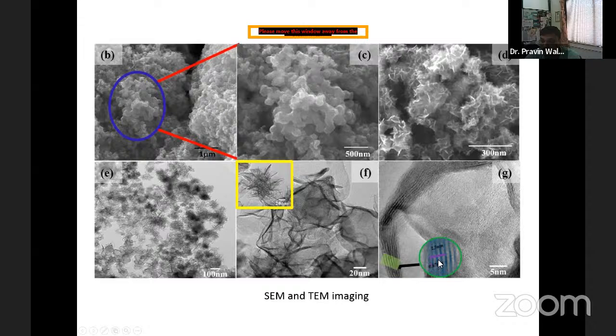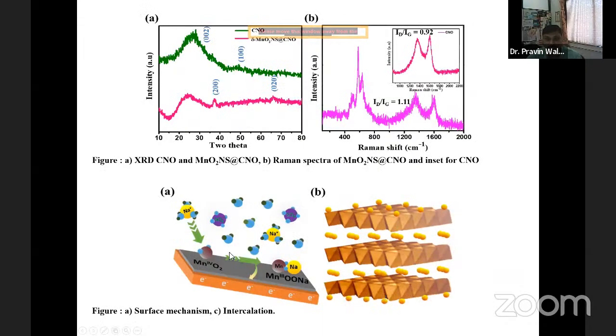These 7 to 8 layers are highly favorable for ion intercalation within those layers. So the ions will go inside the layers, and they will have adsorption on the surface, but at the same time they will try to intercalate into these particular layers. Therefore we call it an intercalated pseudo-capacitive storage.